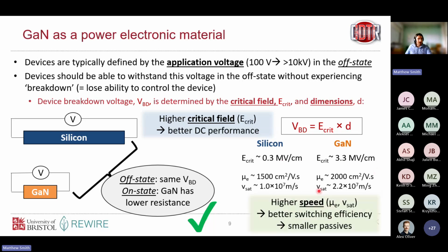And actually, gallium nitride has these other benefits as well. I mentioned mobility and saturation velocity earlier. How quickly the carriers move through the material is very important because as we're opening and closing our channel, so we're essentially charging and discharging our gate capacitor, it means the carriers are able to move more quickly through the device. That's what these numbers here, mobility and saturation velocity, essentially represent: how quickly the carriers move, which is really important for how quickly we can switch on and off our devices.